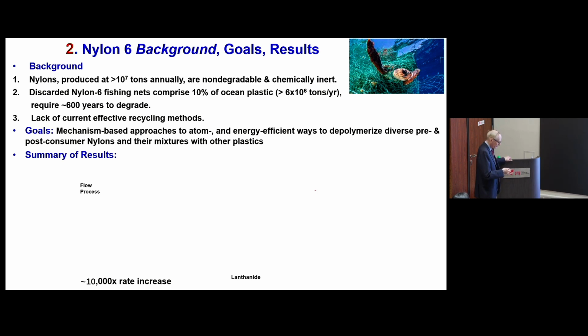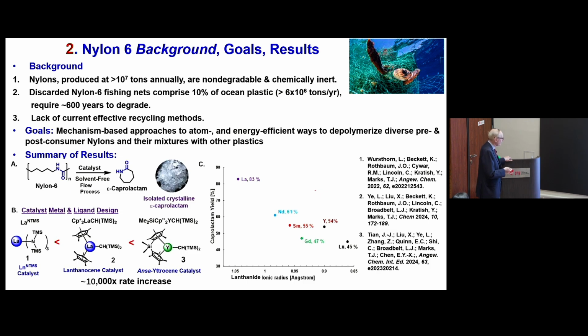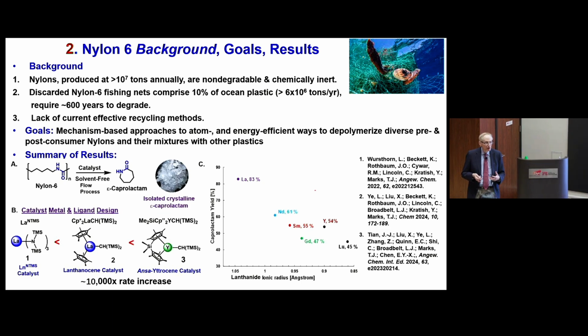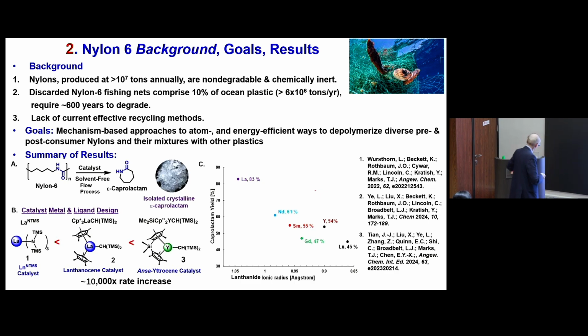deconstructing nylon. And so we set out to do that. And I'll get into some of the details, but it's very much like the PET. We're going to use a reactor, a catalyst, and no solvent. And the caprolactam just sublimes right out, and you get it as very pure crystals. And if you say, well, there's probably no real mechanism going on. Well, as I change, and we'll start with this catalyst, and then go to this one, and then to this one, the rate increases by 10,000-fold. And you can see as I change the ionic radius of the lanthanide, the rate slows down. So we want a large ionic radius, and let's get into the mechanism and then some of the ramifications.